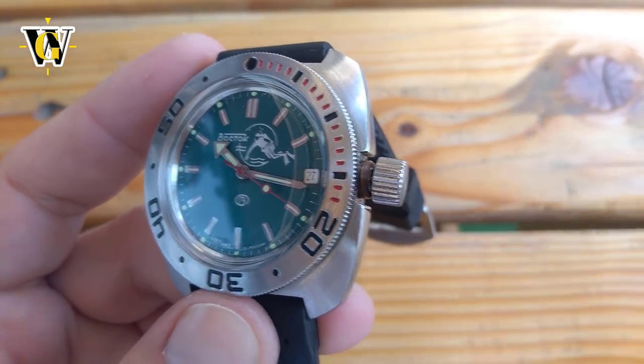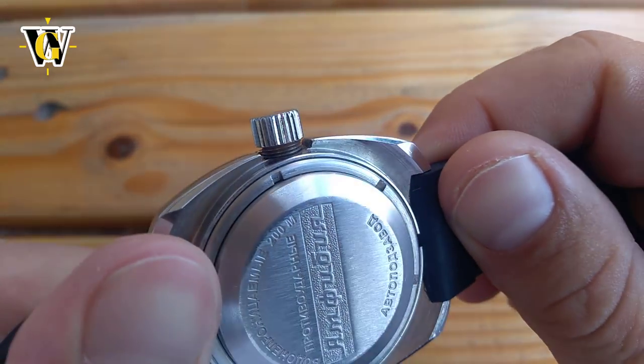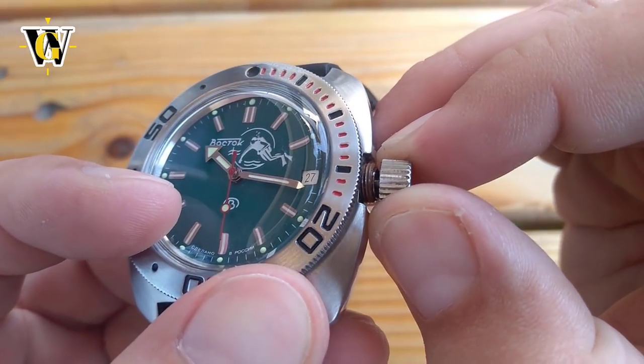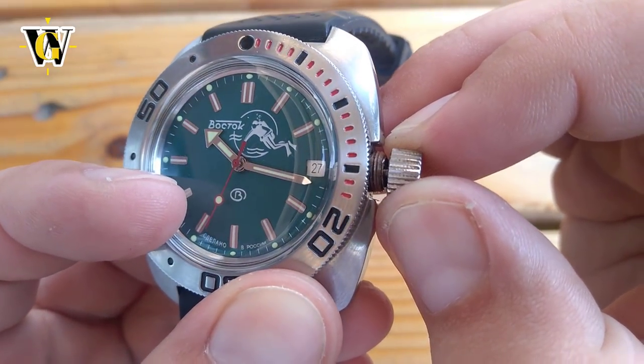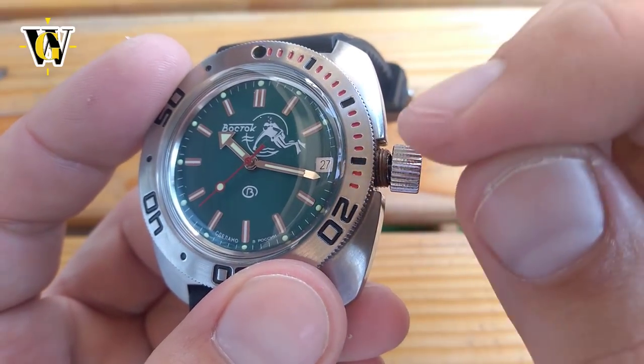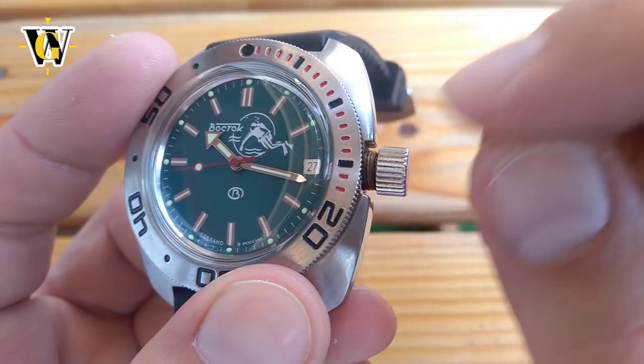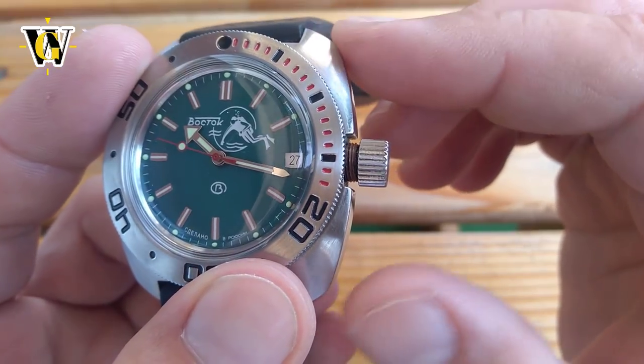The whole crown tube was corroded. And since the watch was not used in seawater and wasn't really used for swimming yet — other than getting wet from an occasional rain — all it got was a lot of my sweat, since we do get hot and humid here. This made me realize that my sweat was probably the electrolyte, and since the Amphibia has a stainless steel case and a chrome plated brass crown, it created a reaction and as a result, corrosion.